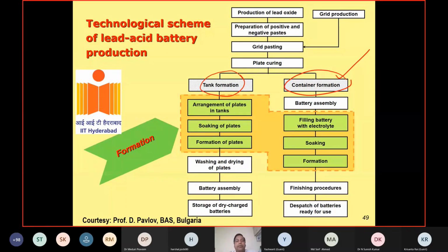In many cases, many flooded systems, they do tank formation. What they do actually, they take 200, 300, or 500 electrodes, and they take counter electrodes, and in 1.1 molar sulfuric acid, they do the formation. They do the charging for a long time, maybe 48 hours, 100 hours, and then fully charge it. That is flooded, and that's also very good actually. We have seen. And as a container formation, what they do, I'll come to the next slide.